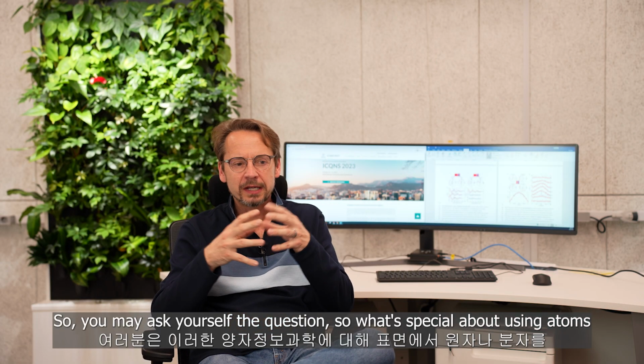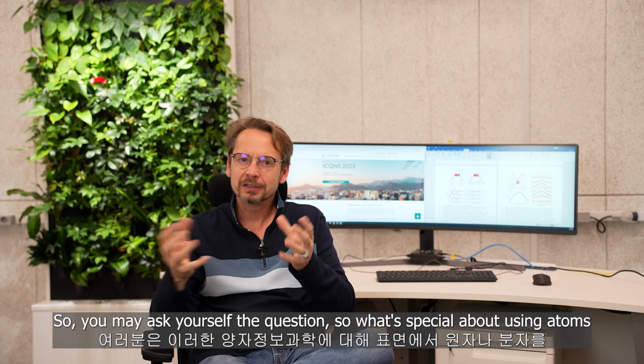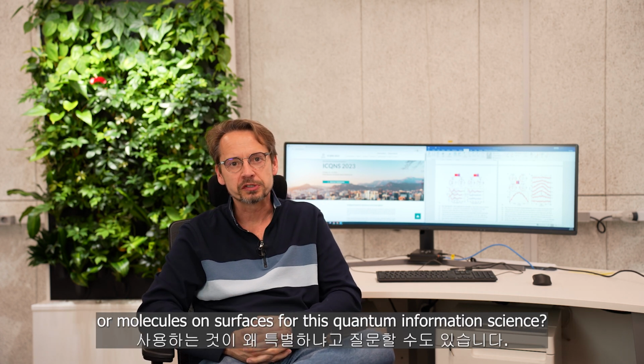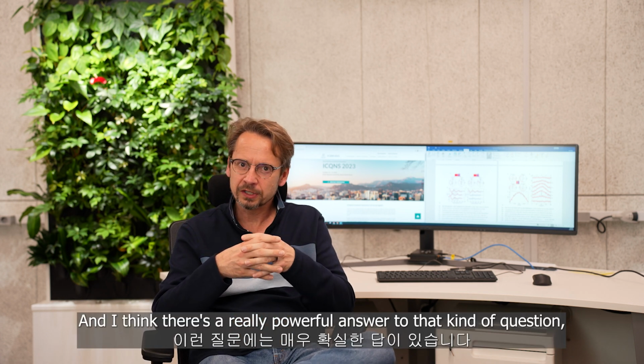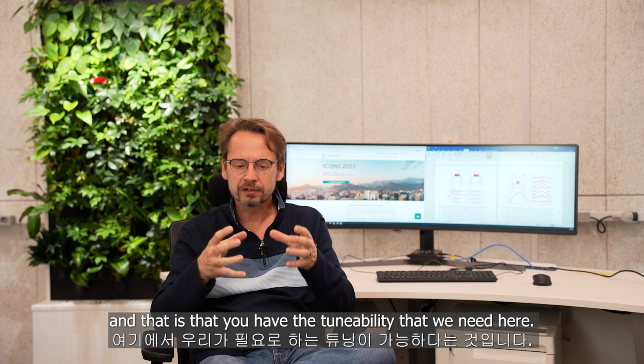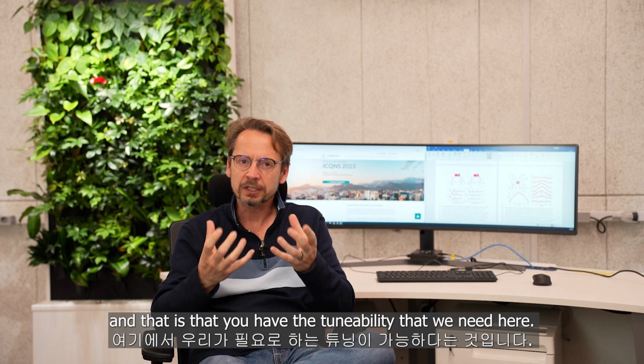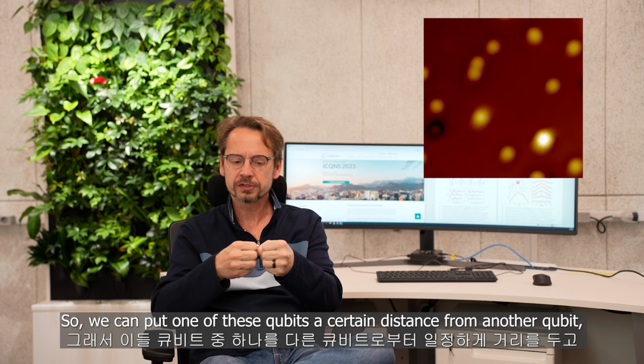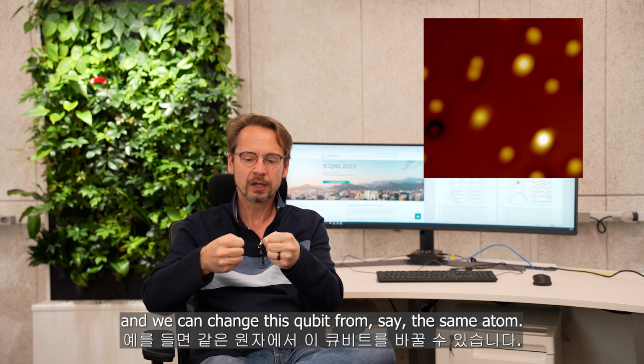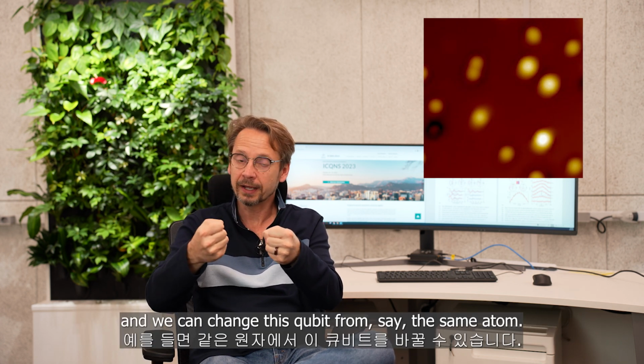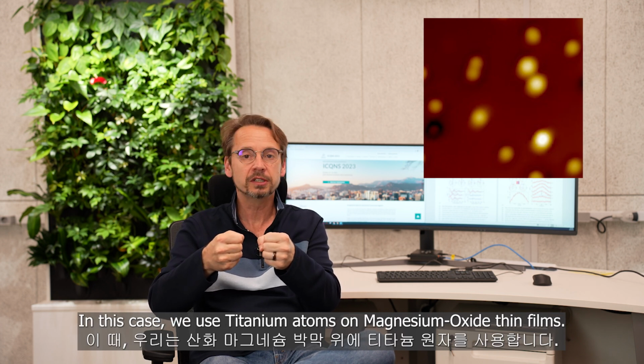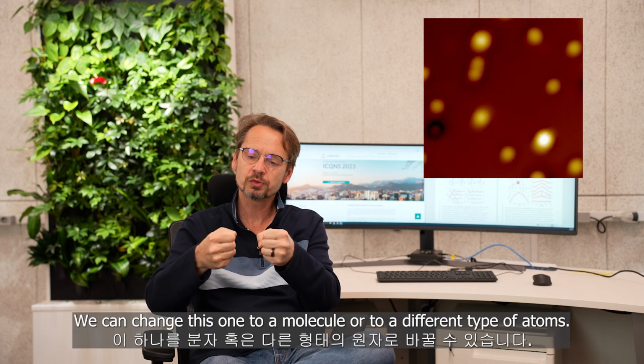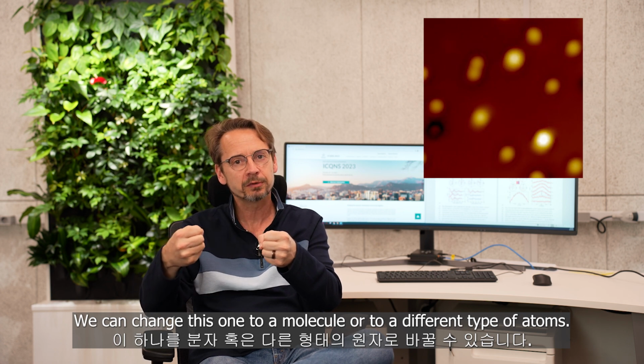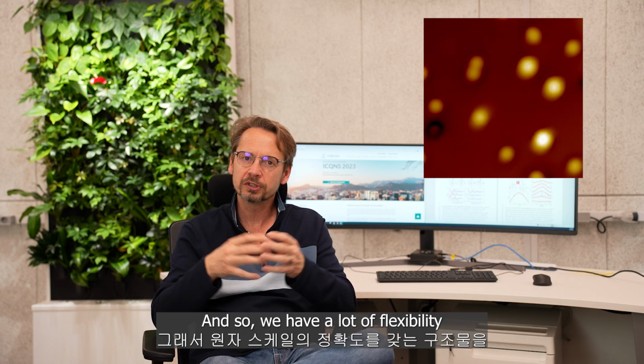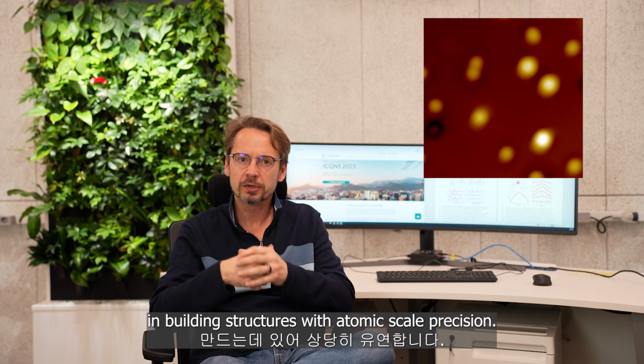So you may ask yourself the question, what's special about using atoms or molecules on surfaces, right, for this quantum information science? And I think there's a really powerful answer to that kind of question, and that is that you have the tunability that we need here. So we can put one of these qubits a certain distance from another qubit, and we can change this qubit from, say, the same atom. In this case, we use titanium atoms on magnesium oxide thin films. We can change this one to a molecule or to a different type of atoms. And so we have a lot of flexibility in building structures with atomic scale precision.